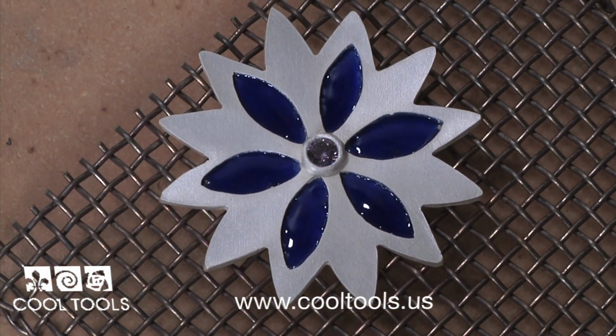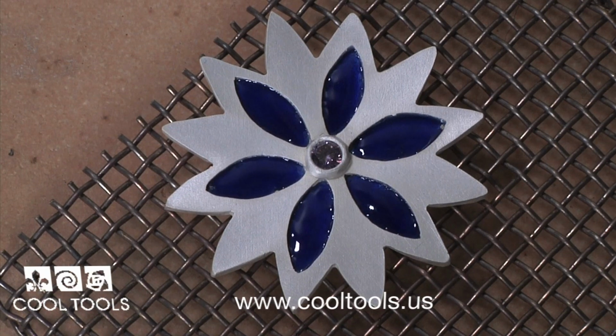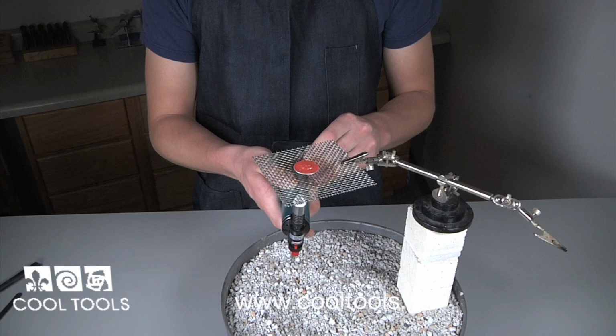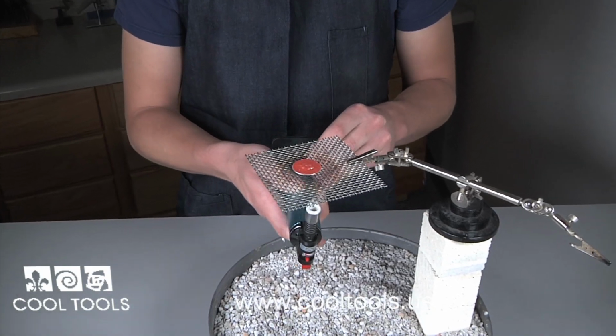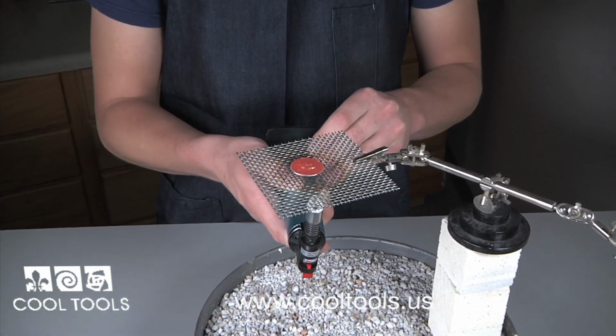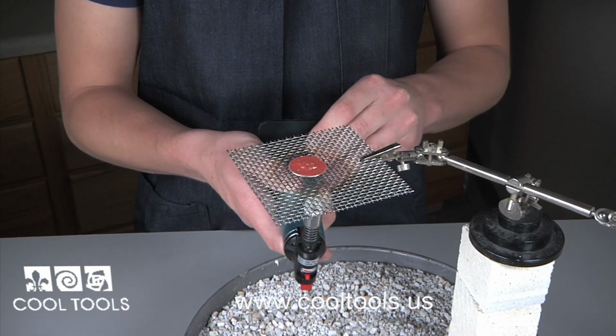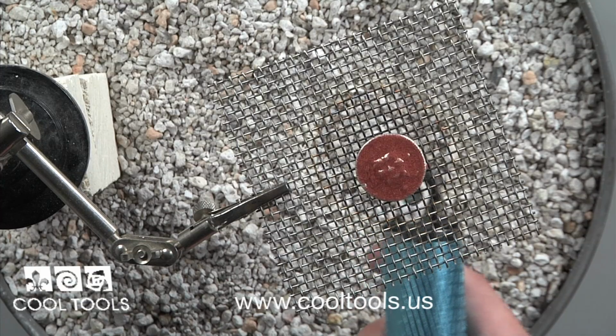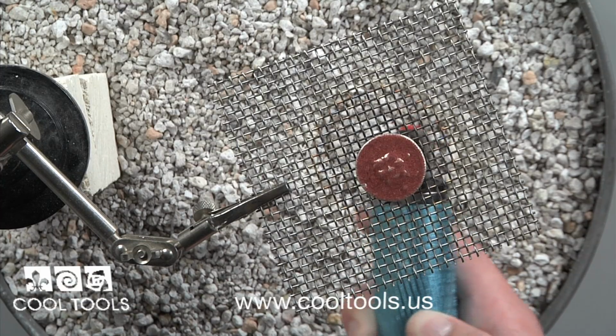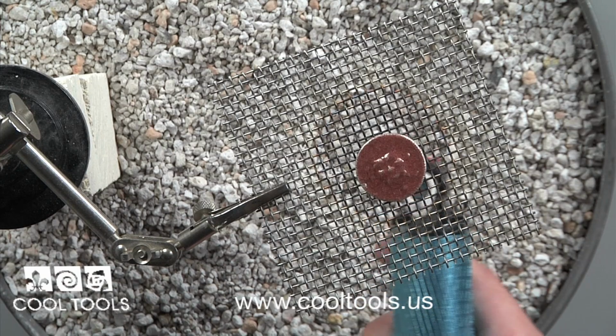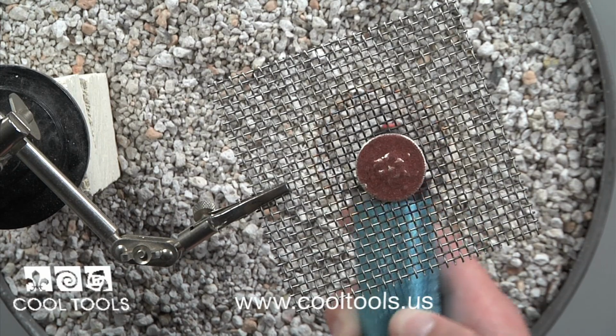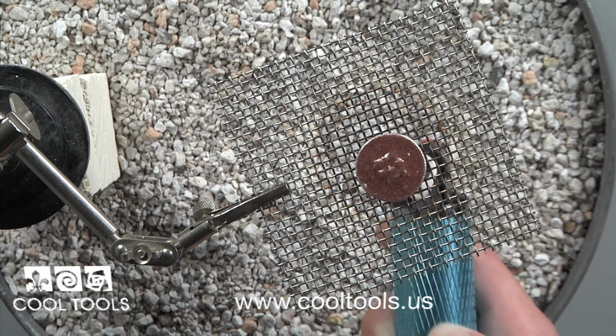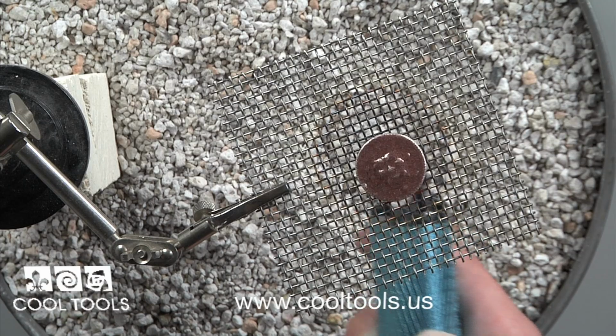You can also fire your pieces in an ultralight kiln, on a gas stovetop, and torch fire. Torch firing can be somewhat tricky. Set your piece on the rack and turn your torch on. Move your torch in a circular pattern around the underside of the piece. I'm using red enamel, which temporarily turns black during firing. Don't be alarmed, the original red coloration will return.